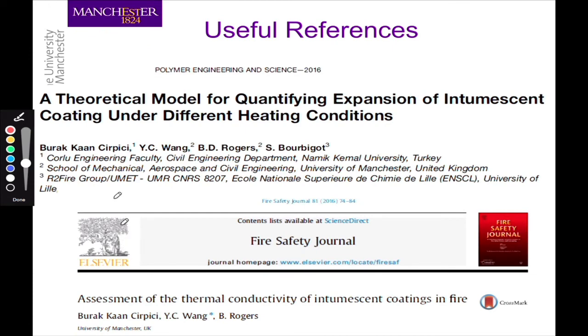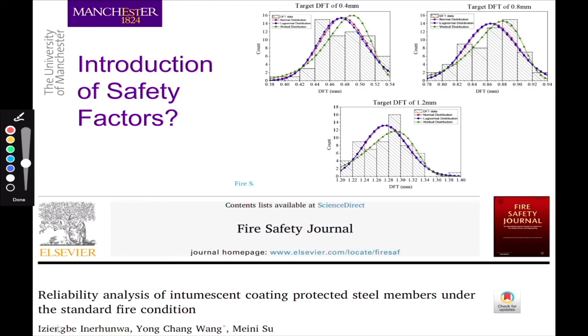And if you're interested, we have published a couple of papers. One is about the expansion process, and one is then to convert from expansion to thermal conductivity on intumescent coatings. Another piece of research which we've done on intumescent coatings is to look at the variabilities. As I said, we have adopted a theoretical solution for an idealized situation. Of course, real life is not idealized, so there are variabilities. There's also another source of variability, that is the thickness of intumescent coatings, the so-called dry film thickness.